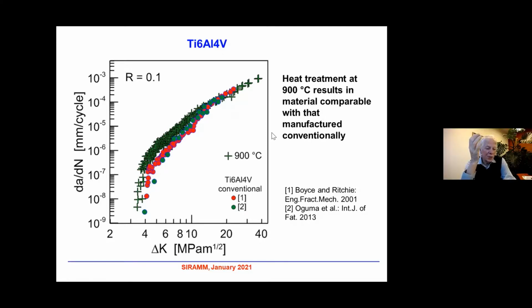Exactly. I wanted to say that many parameters which are set for this production can strongly influence the fatigue parameters. It is not the case of, for example, tensile properties. There the influence is much weaker. However, in the case of fatigue, it has to be taken into account, and it is really important to test material from the point of view of defects and microstructure, simply to be careful.